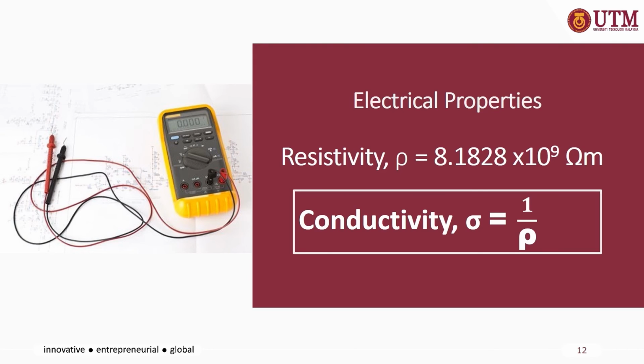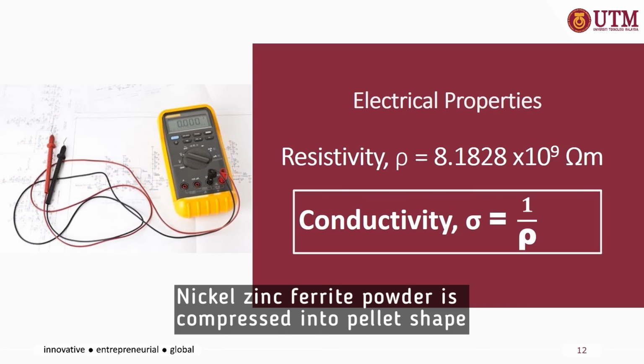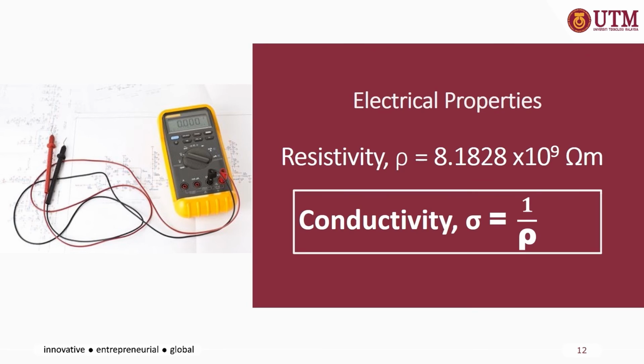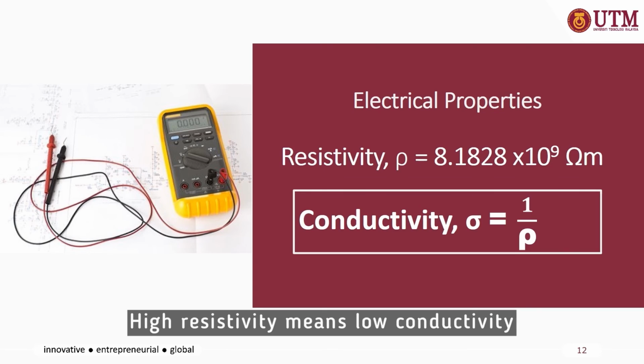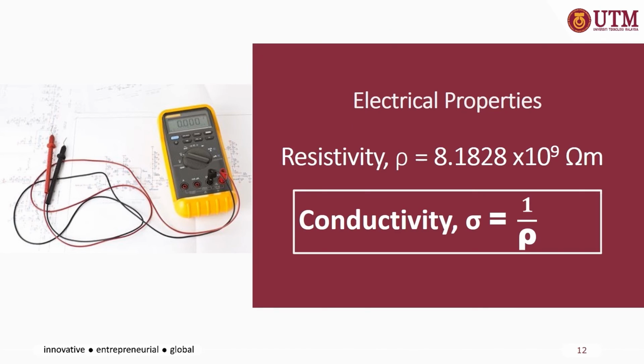And for the conductivity test, we are using a digital multimeter with 2 probes. However, before beginning the testing, nickel-zinc-ferrite powder is compressed to pellet shape as a better way to analyze the electrical properties. From the research, the resistivity is the reciprocal of conductivity. High resistivity means low conductivity because they are inversely proportional to each other. The resistivity of nickel-zinc-ferrite particle is noted to be around 8.1828 times 10 to the power of 9 ohm meter, showing that it exhibits electrical properties at a sintering temperature of 1000 degrees Celsius.